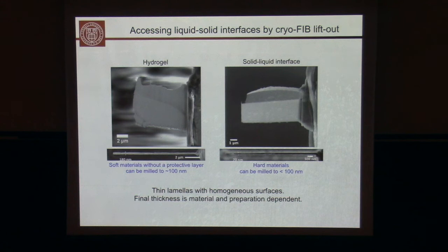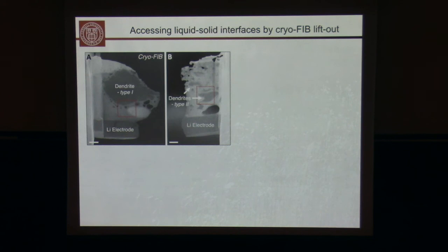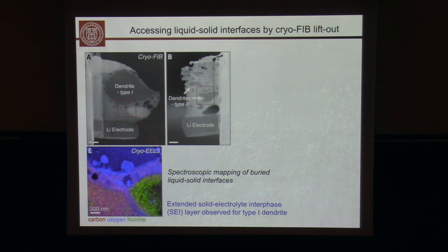So, once you figure this out, you can put it in the TEM, or cryo-TEM, and you right away see our two types of dendrites. That was the large one. This was the smaller one. You see how it winds through the electrolyte. Remember that as it winds, we are cutting at a random cross-section, and so sometimes you don't see the continuation, but it's because it's out of the plane. Down at the bottom is the lithium electrode, and so we are interested both at this interface, but also what happens around the dendrite, which is an important problem, and it's the formation of this solid electrolyte interface.